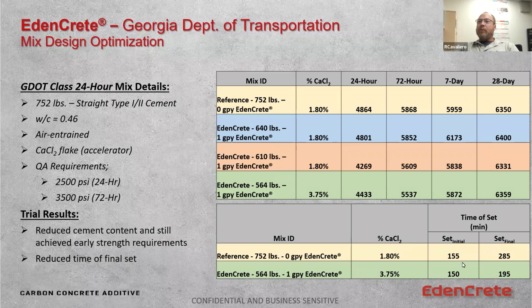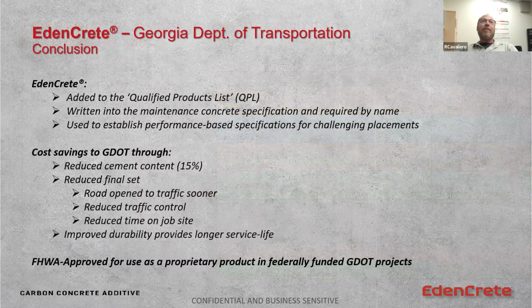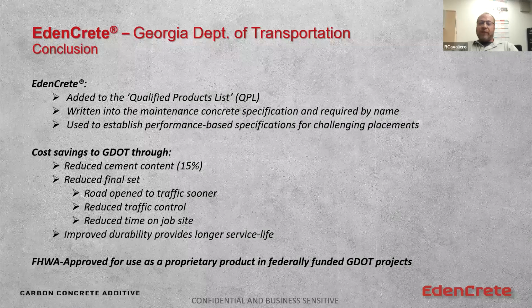We then ran set times, and we saw that initial set was negligibly affected, and final set was 90 minutes sooner. Right, so this would allow them to get traffic control off the road 90 minutes sooner, saving money, saving traffic, saving a lot of different things that cause problems out on the highway when you're driving home. Ultimately, we were added to their QPL. They wrote us into the maintenance specification by name, and they use EdenCrete to save 15% of the cement across the concrete.